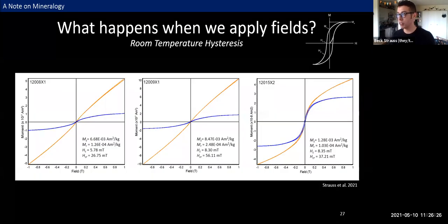Now, here are loops from representative subsamples of each of my samples. We've got our applied field in Teslas on the x-axis and our measured magnetic moment on the y. And I have our raw data in orange and the corrected data in blue. I've also extracted some coercivity and magnetization parameters that define the shape and size of each loop. And this is where it actually starts to get interesting, because since hysteresis loops have been a standard practice for so long, this lets us start thinking about comparing our results with data that goes back to the Apollo era. So we can ask how other Apollo samples compare and think about sources of variation in fidelity limits beyond just my three samples.